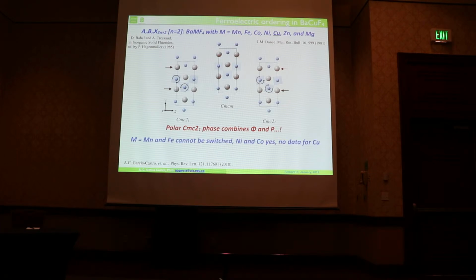Additionally, we have to mention that these two phases have been reported to be polar, but the switching hasn't been reported yet. However, the switching in the nickel and the cobalt has already been shown, but there is no data for copper. And there is something special with copper that I will show here. Additionally, there is no weak ferromagnetism for the iron, nickel and cobalt cases, and only weak antiferromagnetism exists in the structure. But is it there for copper?